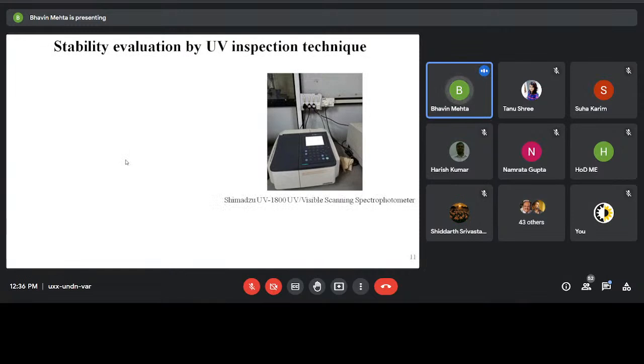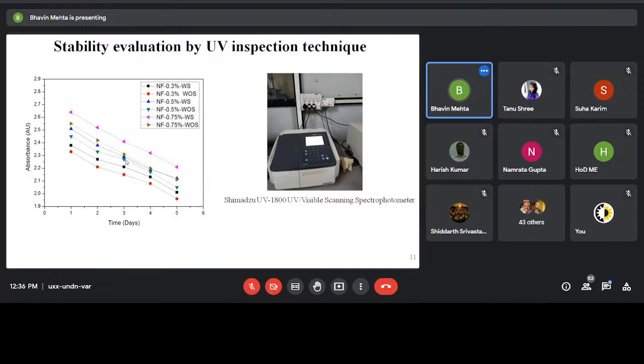Then we have used the UV spectrometer, and we have tested this fluid for continuous 5 days, and for various concentrations, 0.3%, 0.5%, 0.75%. And we found that the drop in the absorbance is negligible during the 5 days. So it shows the better stability.